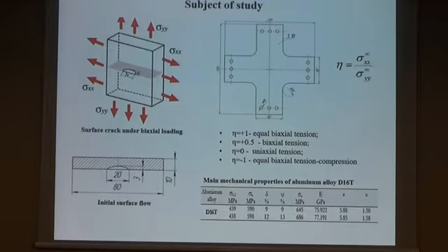The subject of this study are cruciform specimens with surface cracks. Surface crack growth study was performed for equibiaxial tension, biaxial tension 0.5, uniaxial tension, and equal biaxial tension-compression. All tests were performed for aluminium alloy D16T, and its main mechanical properties are listed in this table.